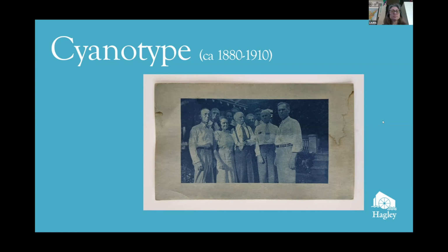The sensitized paper is simply exposed to sunlight with the negative or with ultraviolet lamps, and then it is followed by a rinse in water to complete the process. Cyanotypes were commonly used as a proof process for the preliminary assessment of a negative. The Prussian blue pigment can revert to a white form when it's exposed to light, causing bleaching of the image. This change is thought to be largely reversible with the return of the print to dark storage. It's unknown if it's 100% reversible, however.